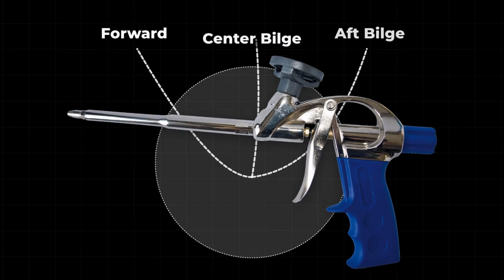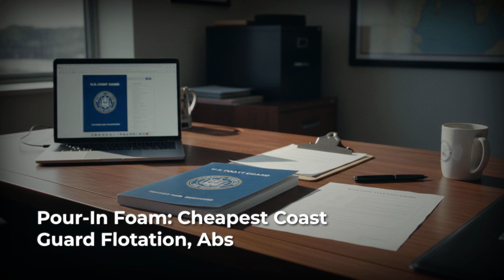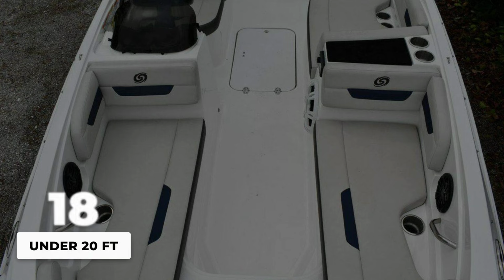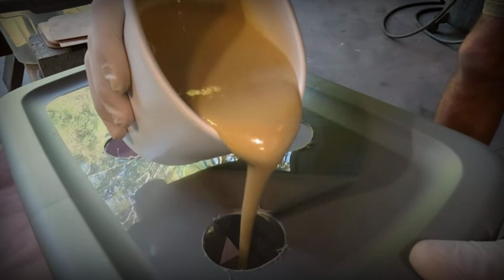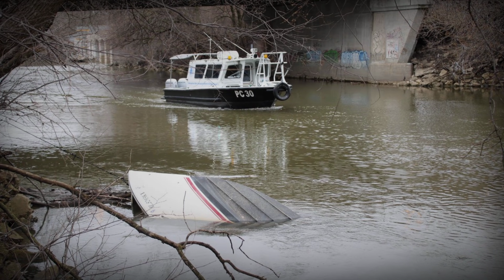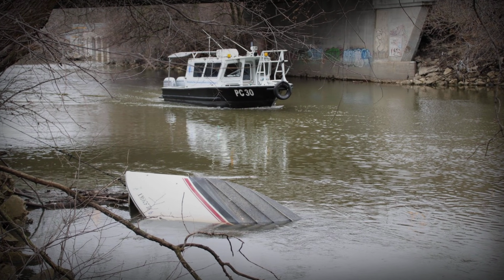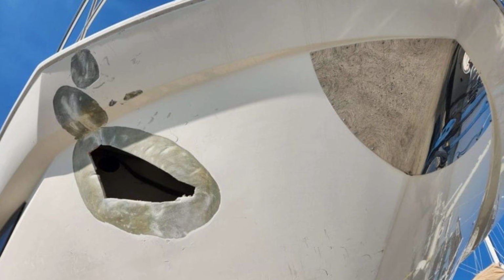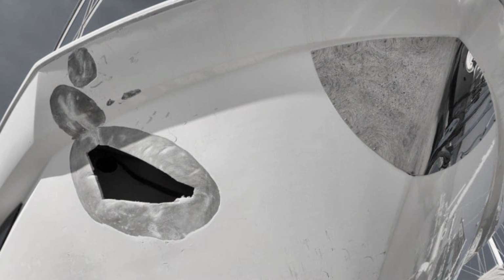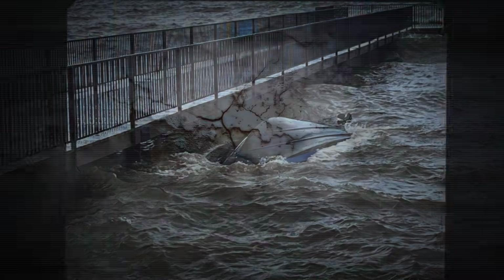Pour-in foam. Most builders fill hull cavities with 2 pound per cubic foot polyurethane foam. It's the cheapest option that meets Coast Guard flotation requirements. But here's what the brochure won't mention. Those flotation requirements only apply to boats under 20 feet. Your 22-foot center console, your 24-foot bay boat, that 26-foot fishing machine you just financed, zero federal flotation requirement. If it swamps, it sinks.